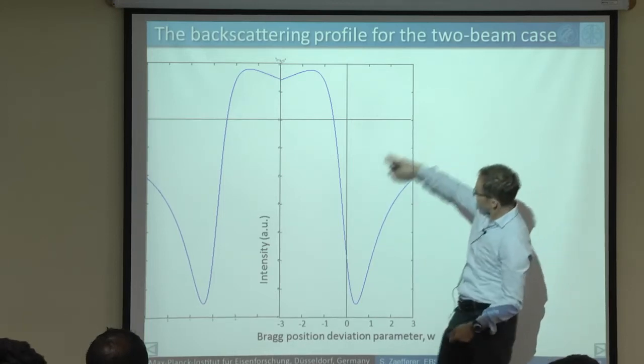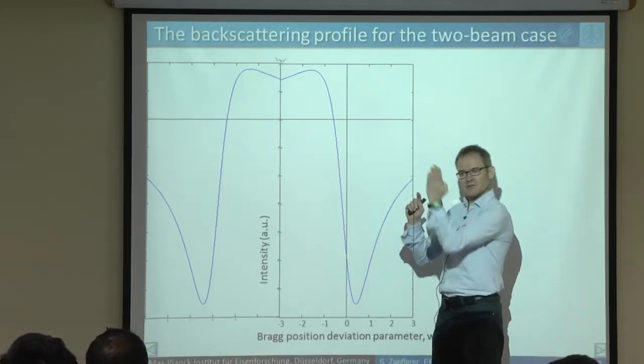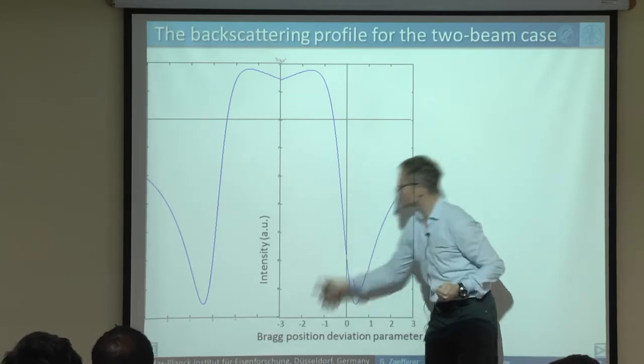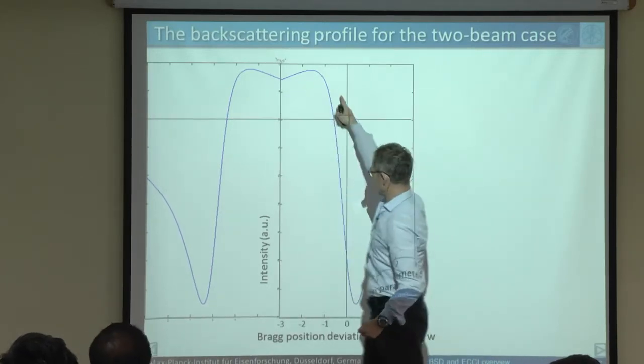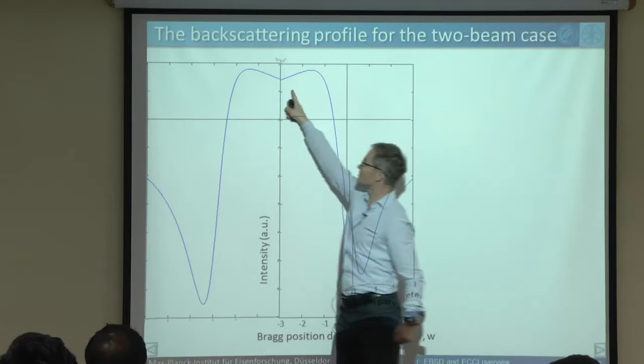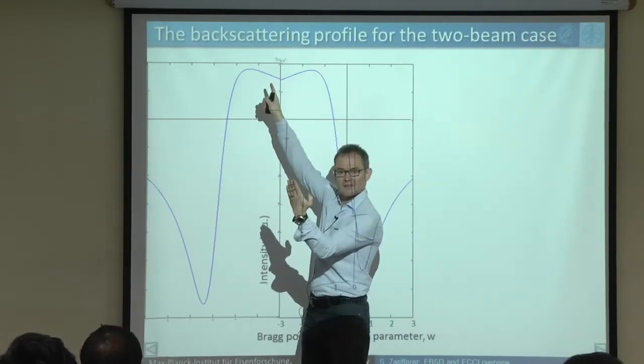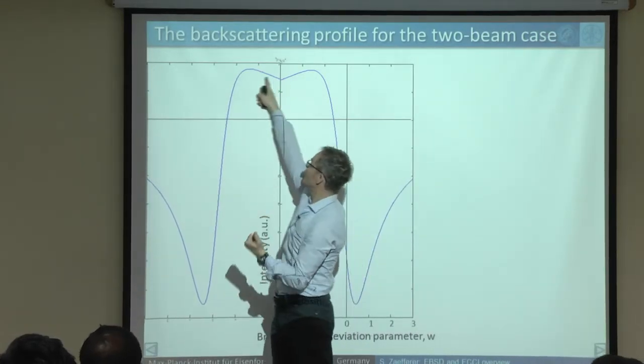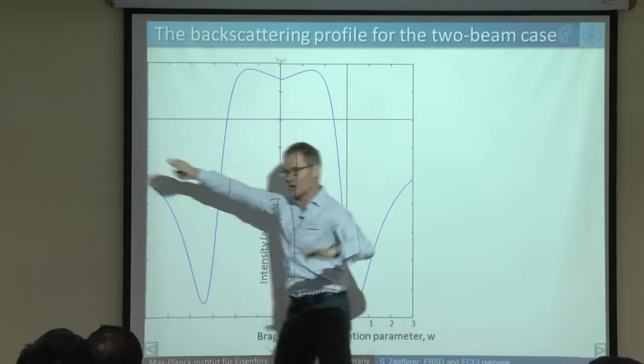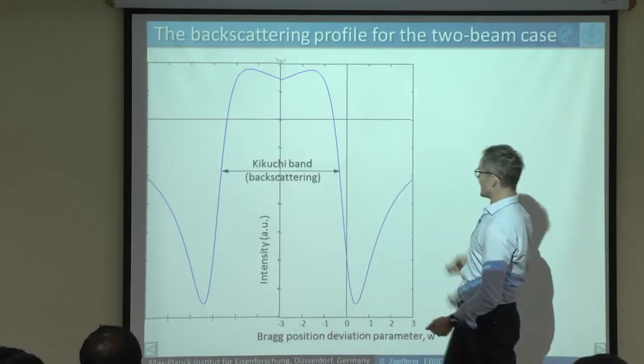Yeah? And quite in contrary, when we're getting closer to the lattice plane, so the W becomes negative, then we are getting high intensity. We have a dark line, high intensity, and then we are switching over to the backside of the crystal lattice planes, high intensity, dark line, and normal intensity again. So, and we have seen that already.